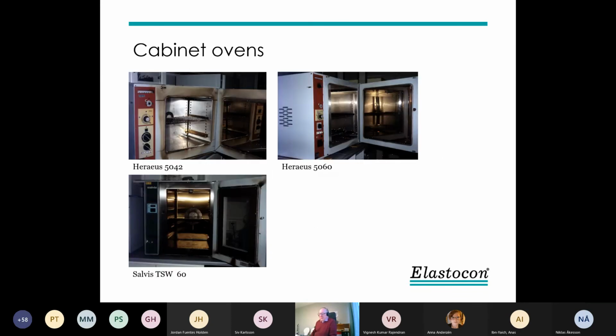Look at cabinet ovens. Originally there were no cabinet ovens really meeting the requirements for heat aging. Here are some we looked at in that project we made, where we took cabinets from some of the participating labs and we measured them. These were standard lab ovens. So you can see they normally have a fan in the back, which means that it blows quite high air speed, especially in the center and in the sides. So the air comes out on both sides around the baffle and sucks in the center.